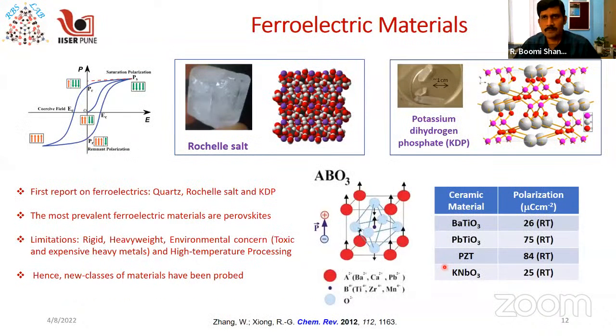So the typical ferroelectric materials, as I told, are Rochelle salt, which is sodium potassium tartrate, and potassium dihydrogen phosphate. However, the ceramics are dominant in this field, because they are typically very robust. So a ferroelectric loop looks like this. When you apply an external electric field, the material gets polarized and gets saturated at a critical electric field. Okay, so this is called a saturation. No, this is not a coercive field. The polarization gets saturated, which is called the saturation polarization, at a particular electric field.